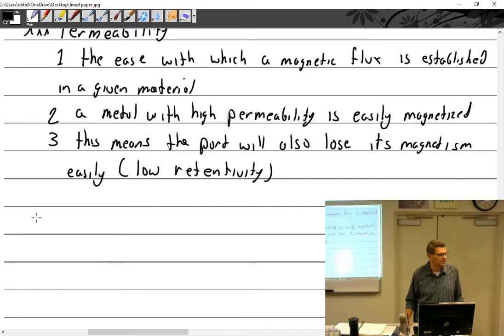Why should it matter? You see what you think is a crack and then you just wipe it off with your hand and spray it again. It shouldn't matter if it's got enough retentivity in it. It should work. That's the thing. It should. But is it a part that has the retentivity? So if you're reading something that has the process control and it says this part must be inspected using wet continuous, even a crankshaft, yeah, I could sit there and argue all day that I can probably get the same indication out of it with residual, but there isn't the same amount of magnetism.